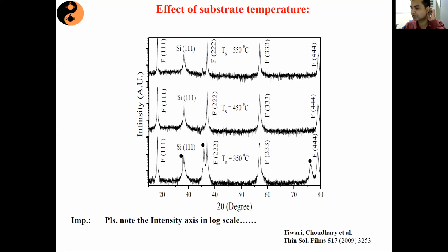Because suppose your impurity phase is very low in intensity, let us assume 100, and your main film peak is say around 1 lakh. As compared to 1 lakh, if you plot that on a linear scale, 100 cannot be noticed easily. But the moment you put them on a log scale, this 1 lakh will come down to 5 and 100 becomes 2. So 2 can be easily probed in contrast to 5. That is why it is very important to plot the thin film's X-ray diffraction on the log scale.